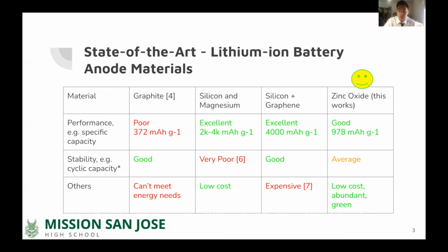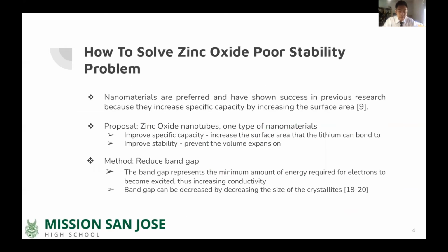As zinc is abundant on Earth and easily recyclable, it is a great material to keep the environment clean. Another advantage is that it has a higher lithium-ion diffusion coefficient compared to other transition metals. Some potential disadvantages are poor electrical conductivity, high volume change during charging and discharging, and poor cyclic capacity. So how do we solve the poor stability problem?